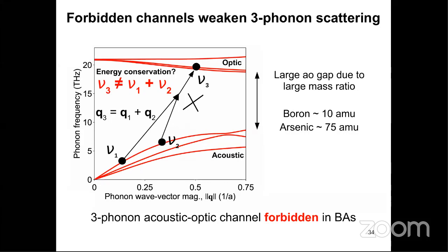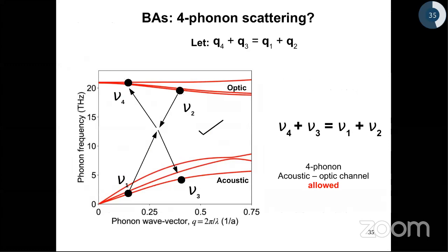incoming phonon energy. And in this case, because of the large gap between the acoustic and optic phonons, this process is completely forbidden. That is, you cannot find any 2 acoustic phonons that can scatter into an optic phonon. So this 3-phonon acoustic-optic scattering channel, which is actually one of the most dominant scattering channels in most other semiconductors, is completely forbidden in boron arsenide. So you remove one scattering channel completely from the picture, the total scattering rates go down, the denominator goes down, the thermal conductivity goes up. And that is the microscopic origin of why boron arsenide has such a high thermal conductivity, even comparable to that of diamond. So naturally, a question will arise at this point.